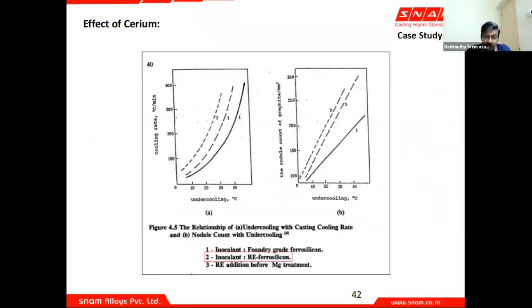So there is a relationship between undercooling and casting cooling rate, and we find that a rare earth based ferrosilicon alloy is midway between a rare earth with magnesium treatment and a foundry grade ferrosilicon. So that is another reason why foundry grade ferrosilicon by itself should not be used. It should be used in conjunction with some other nucleating elements.